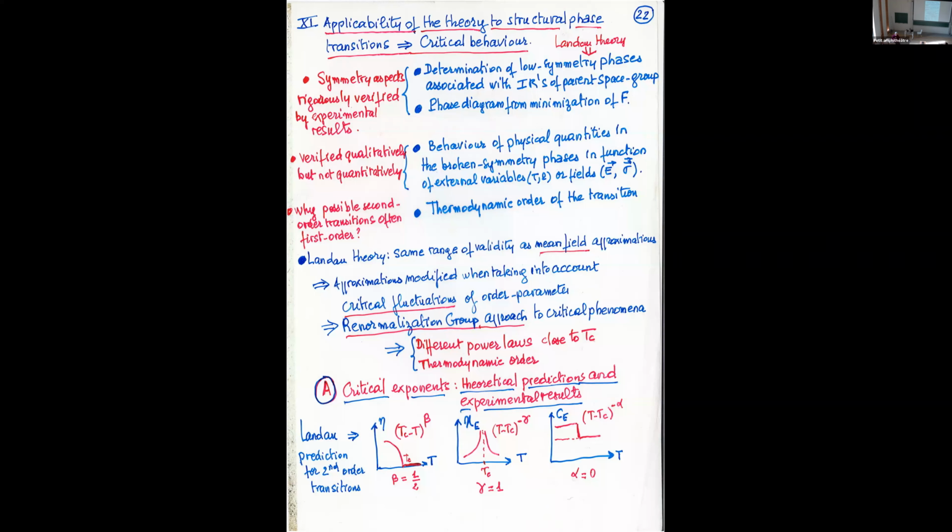And you have a beautiful sequence of two second-order phase transitions in most of the multiferroics. The first one is purely magnetic, but you keep time reversal in the point group. And the second transition is again second order, but you lose the inversion center.